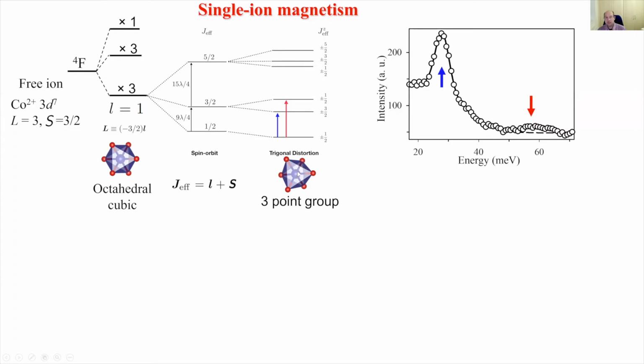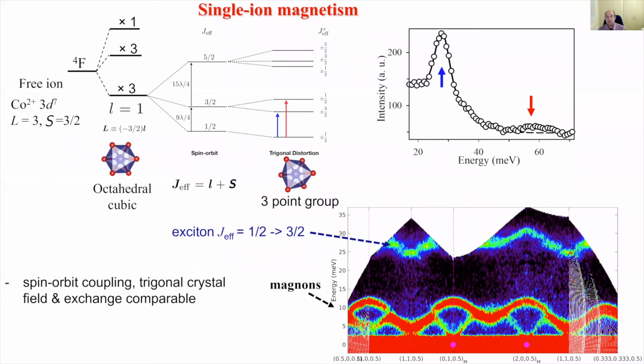And via trigonal splitting, which occurs in the system because the octahedra are compressed along the z-axis, the stacking direction, this gives rise to a splitting here. And indeed, we do see experimentally transitions to these states that we identify with transitions in the trigonally split J 3/2 level. So this is the blue transitions to the first level, and the red one is to the second level. So now measurements on single crystals show that actually this level disperses in reciprocal space in a very similar fashion that mimics the magnon dispersions at low energy.